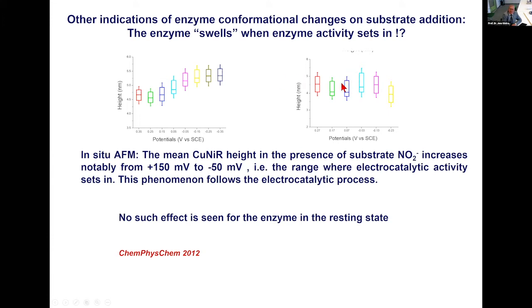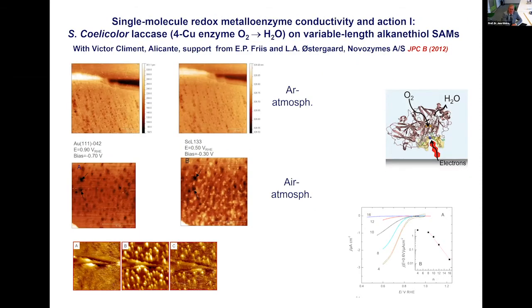This is a common observation, and for nitrite reductase, it's accompanied by another effect, which was a great surprise to us. If there's no substrate and you scan the atomic force microscopy over the potential range where the enzyme is otherwise active, no change. If you let nitrite in, something happens around the potential where electrocatalysis sets in. It is as if the enzyme swells by a whole nanometer. There must be some sort of conformational change, but the nature of this change is something we have not been able to identify.